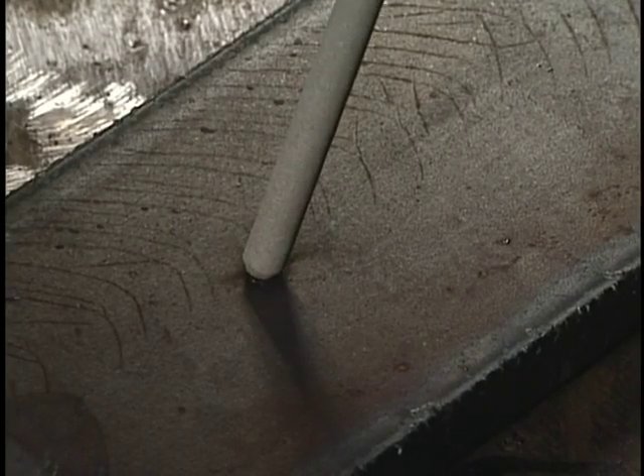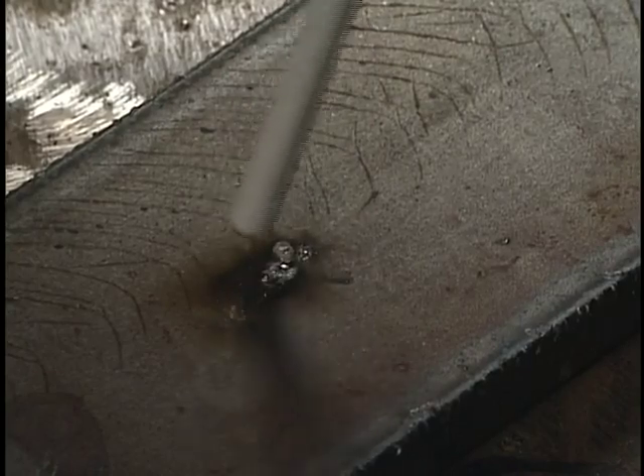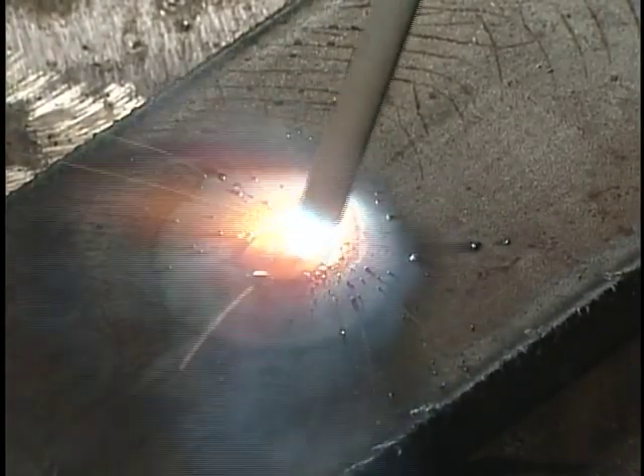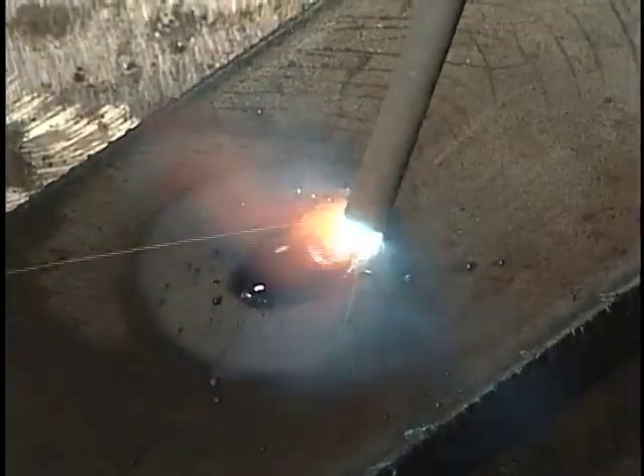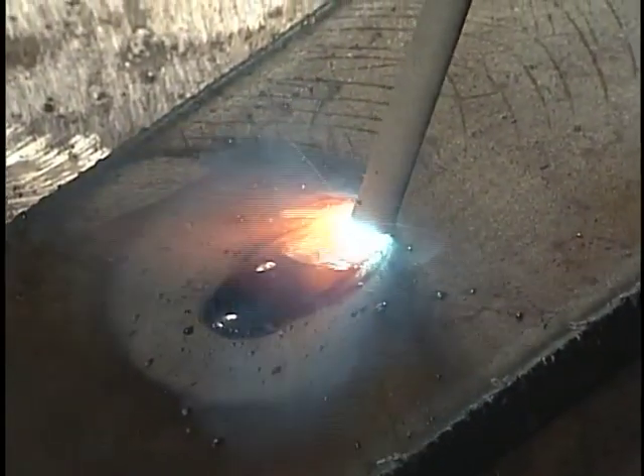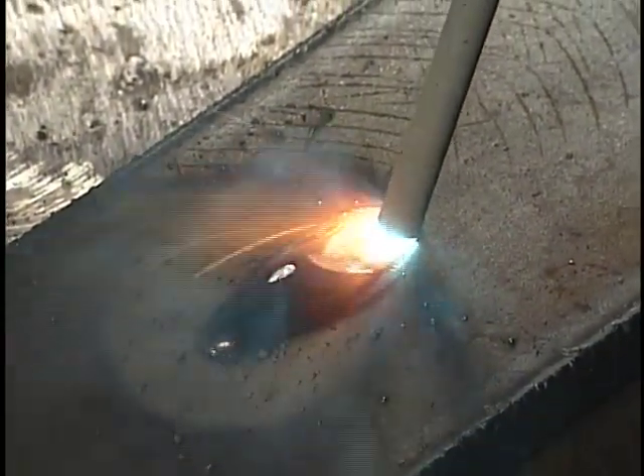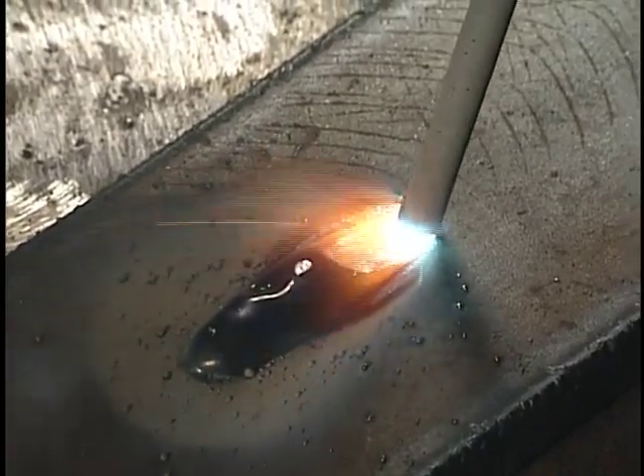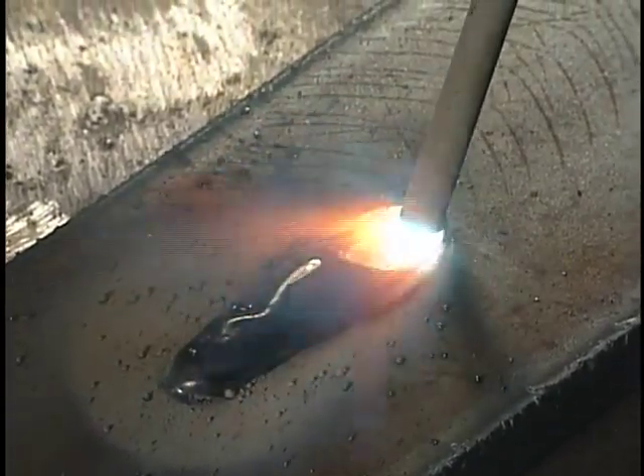The bead is most vulnerable to defects immediately after you begin to generate the arc, because the arc is still unstable and there is not yet enough shield gas. Also at this point, the base metal is still cold, a condition that often leads to weld defects such as incomplete joint penetration and incomplete fusion.